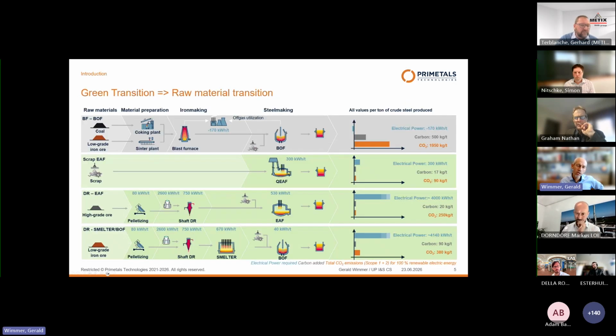So that's why the future green transition will not only include the classical route already known today and very successfully used in a lot of plants. Primetals is doing just one of these plants in Germany for Dillingen, Midrex shaft technology and modern electric arc furnace. We will also need technologies that allow to use low-grade iron ores, which is the majority of iron ores available today. And this requires this new type of furnace, which is simple furnace just doing melting and reduction. No metallurgical refining work, and all the refining work we do in a dedicated aggregate, the BOF converter, and this also explains why this route with these two steps, smelter plus BOF converter, is very interesting for plants already having a BOF converter in operation, and especially plants having very large heat size that is not that easy to transfer to electric arc furnace, like for example POSCO, ThyssenKrupp or the Japanese plants.